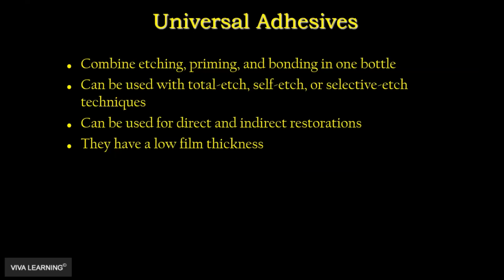One thing that's critical to understand about universal adhesives: if you don't light cure it first, then you will get failures, okay? They go on hydrophilic, which is what we want, especially when bonding to dentin. So you want the adhesive to be hydrophilic, water loving, when it's bonding to dentin. But to bond to resin, you want it to be hydrophobic. So a universal adhesive goes on hydrophilic, and once it's cured, it becomes hydrophobic. So, water repelling, but it has high bond strengths to resins. So that's why it's so important that you light cure your universal adhesive before you place a layer.